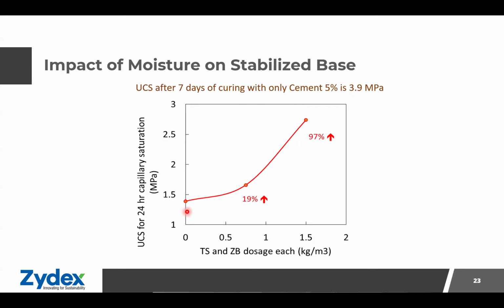But we can retain this value by adding organosilane additives such as Terrasil and Zycobond. Here in this figure, we can see at a dosage of 0.75, we can almost increase the value by 19%. With a higher dosage, we can retain the value by 97%.